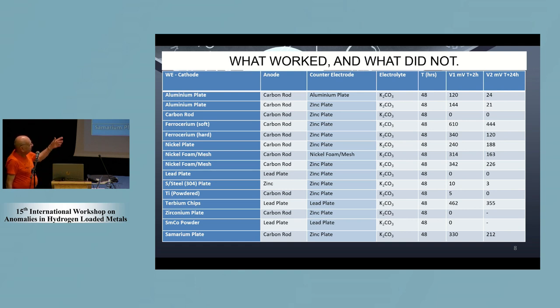You can see it just produced 10 millivolts or something when it was fresh, and just a few, 3 millivolts 48 hours later. All these electrodes, by the way, were oven dry. The process was take it out of the tank, wash the electrolyte off the surface, mostly just under a tap, and so not even distilled water.